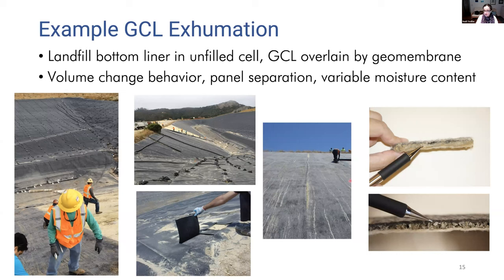In terms of the moisture condition of the GCLs, we observed that there were places along the system where the GCL was relatively wet. We had a material which had a gel structure, a relatively well hydrated material. And in some cases, we were looking at very dry conditions. This material was very similar to the incoming material. You can see the individual bentonite granules in the system. Not much moisture at all entered this system, and the material was looking like the new incoming product.